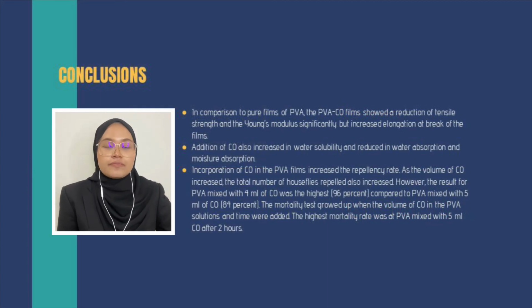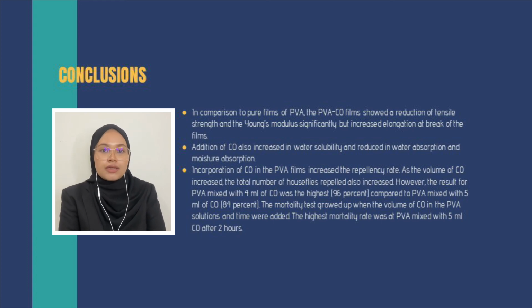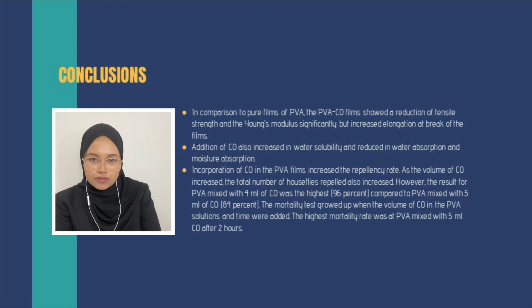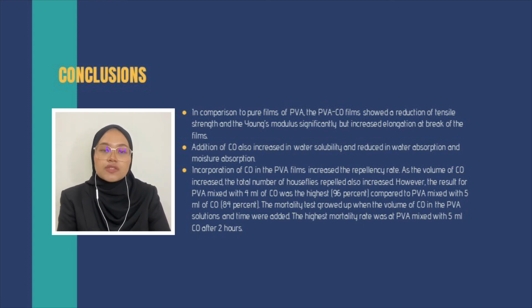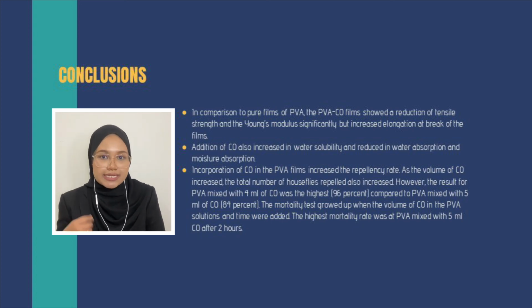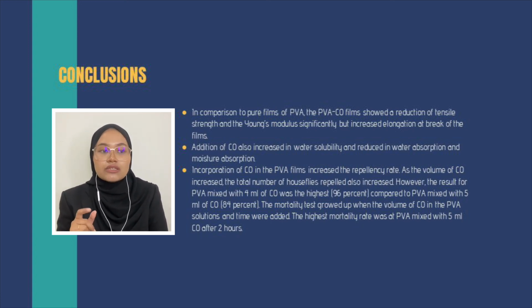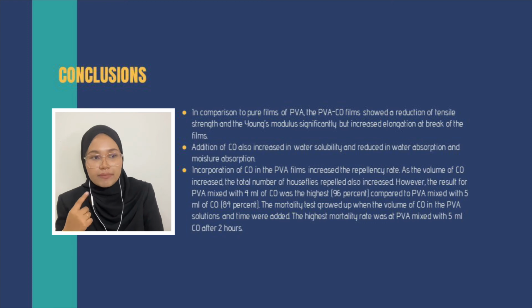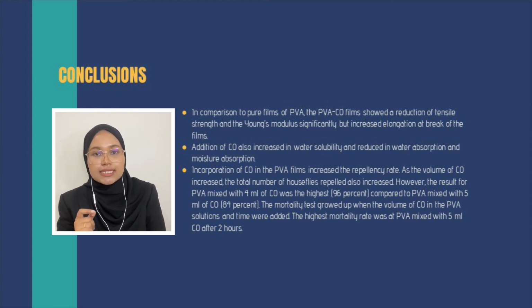To conclude this project, in comparison to pure films of PVA, the PVA CO film showed a reduction of tensile strength and Young's modulus, but increased the elongation at break of the films. The addition of CO also increased water solubility and reduced water absorption and moisture absorption. Incorporation of CO in the PVA films increased the repellency. As the volume of CO increased, the total number of houseflies repelled increased. However, the result for PVA mixed with 4 ml of CO was the highest, which is 96% compared to PVA mixed with 5 ml of CO, which is 84%.